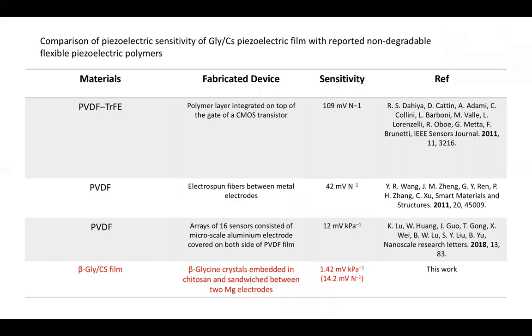And this table shows a comparison of piezoelectric sensitivity of the device with other reported non-degradable piezoelectric polymers such as PVDF and PVDF-TrFE. Although the sensitivity is lower, it is still in quite a good range, and we think the fabrication process can be studied further to control and optimize the crystal structure and enhance the piezoelectric properties.